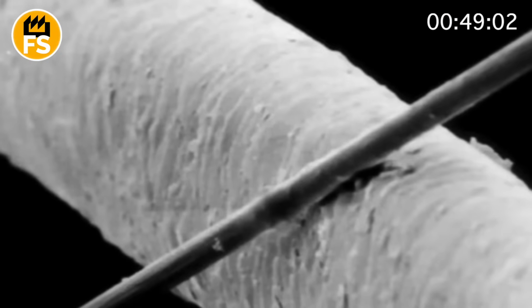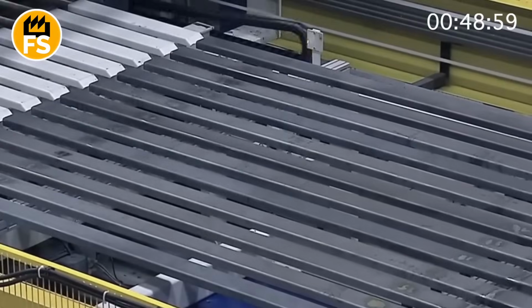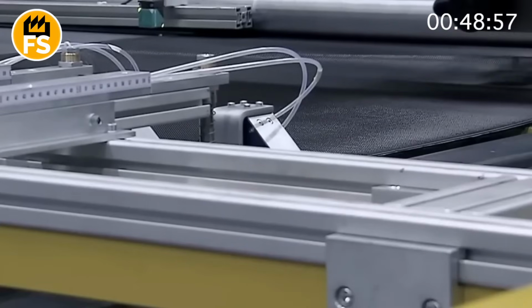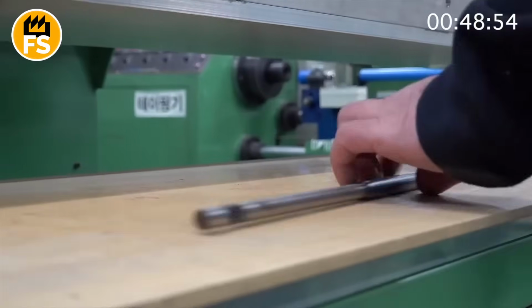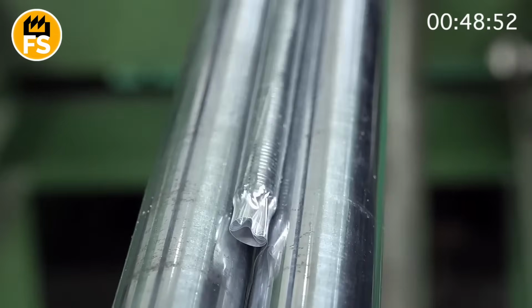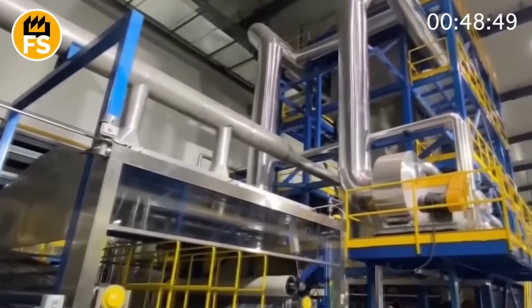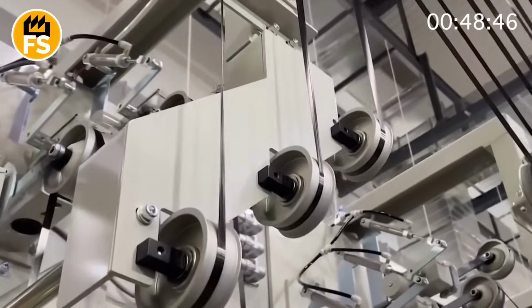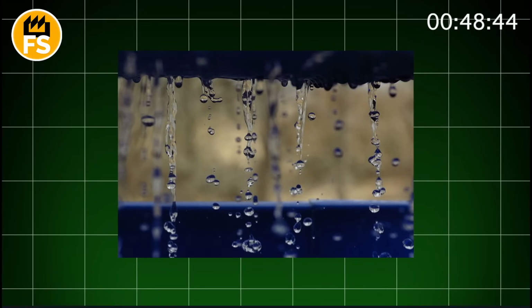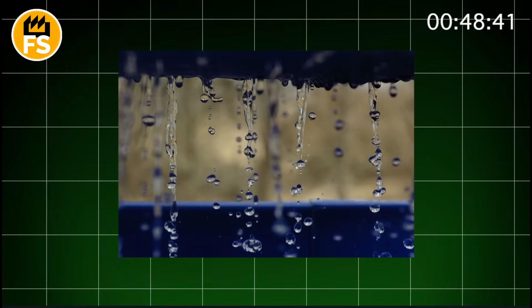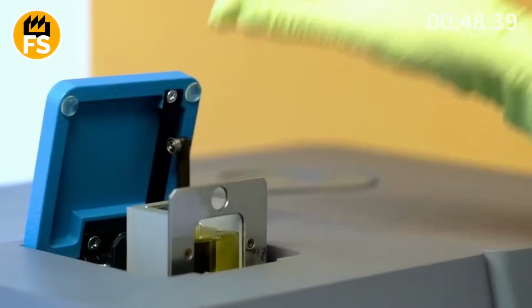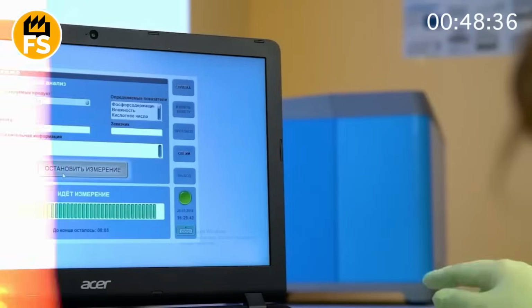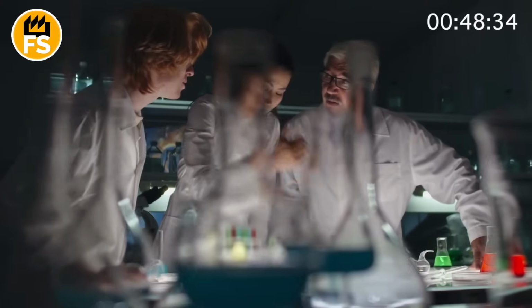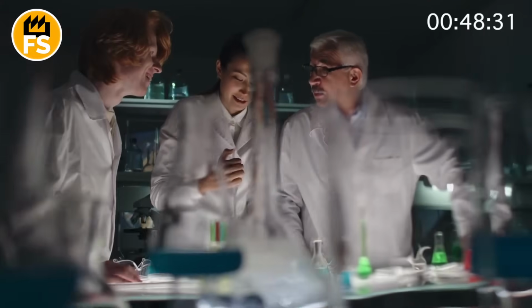And this is critical, because even 1 billionth of an inch of foreign metal or organic matter can cause light scattering or absorption in the fiber optic cable. And then the signal, which was supposed to travel 60 miles without amplification, simply disappears. Raw material for fiber optic cable isn't just washed or filtered, it's purified at the molecular level. Manufacturers often use vapor phase chemistry. Quartz sand is converted into gaseous silicon tetrachloride, which is then distilled, filtered, and deposited as pure vapor. And only then is it converted back into glass.